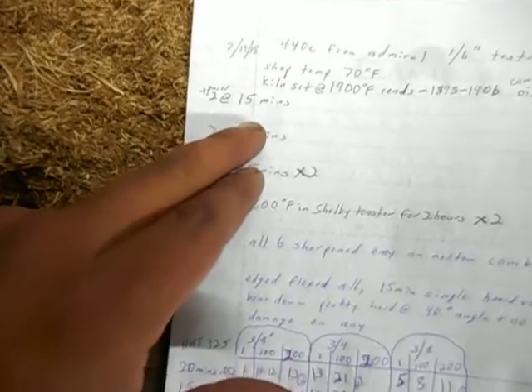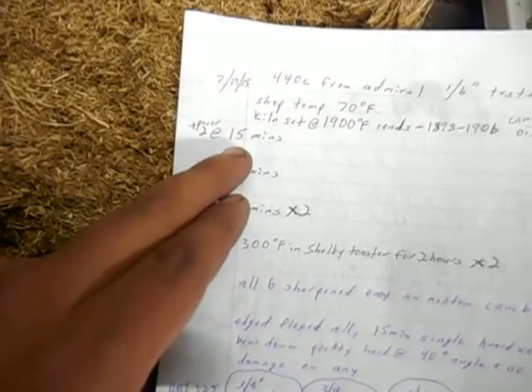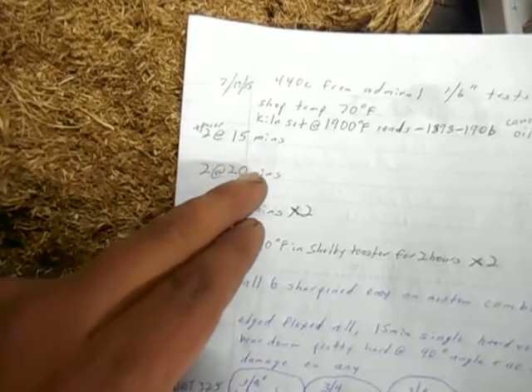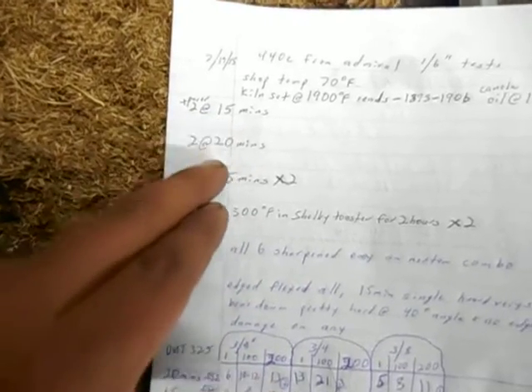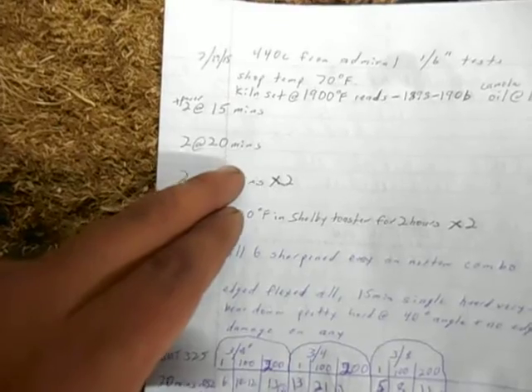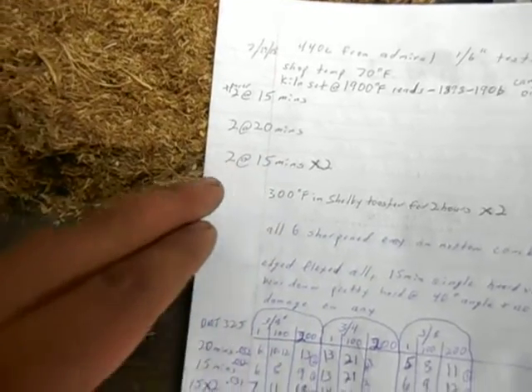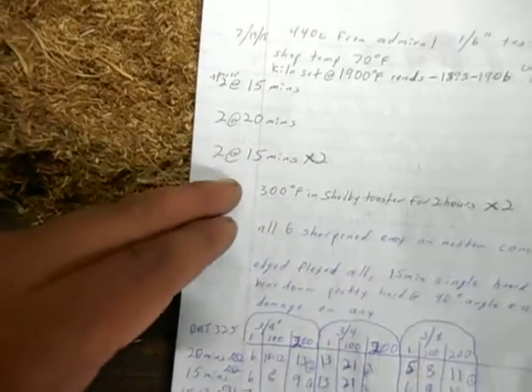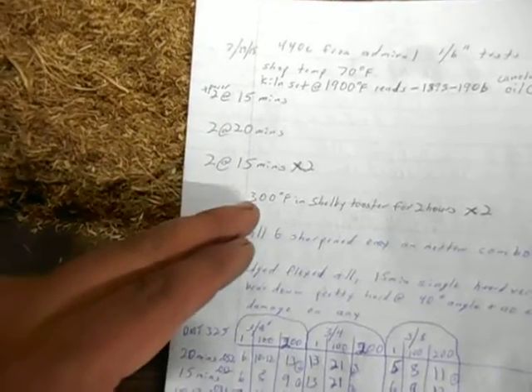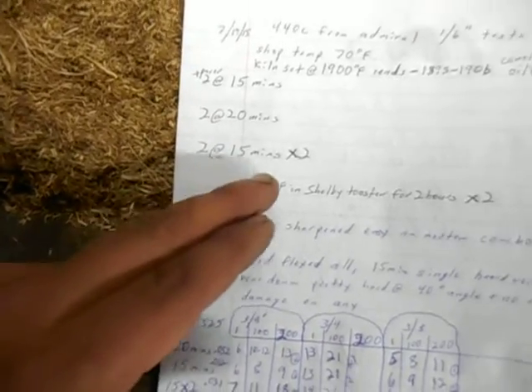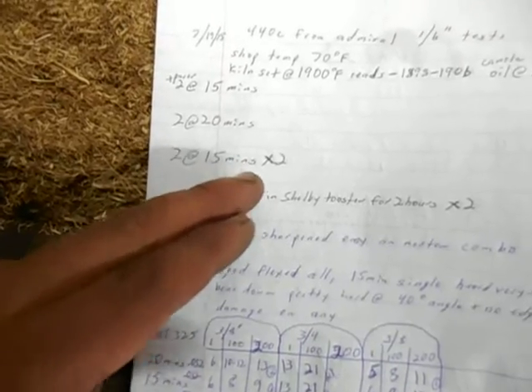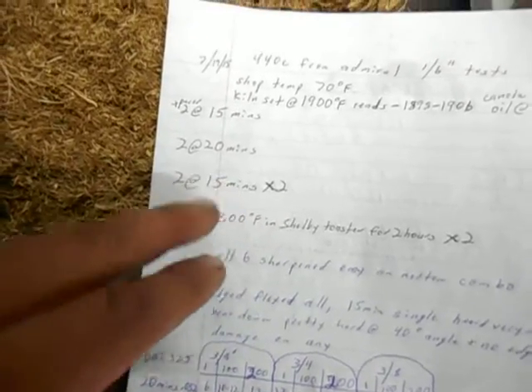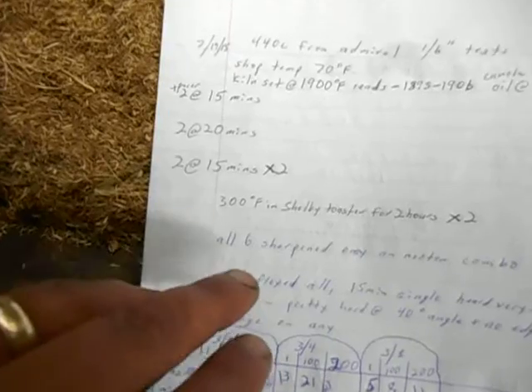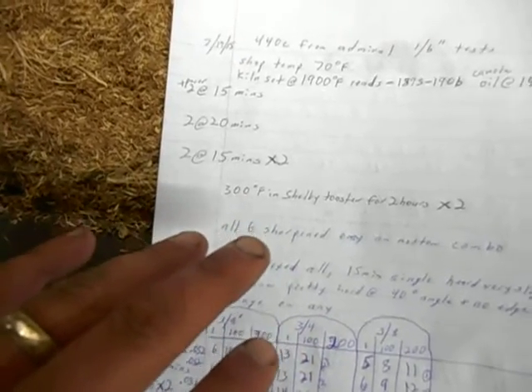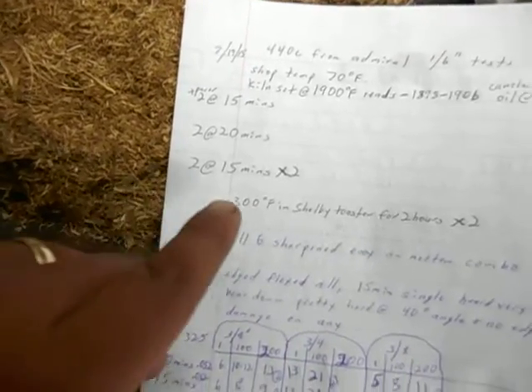But I did the first one at 15 minutes before I quenched it in the canola oil. Or the first two. 2 of them at 20 minutes before I quenched them in the canola oil. And then I do a multiple quench on 1095, 5160, and 52100. So I did 2 of them at 15 minutes and then quenched them twice. So heated it up for 15 minutes, quenched it, let it air cool down to room temp, and then repeated that for the second time.